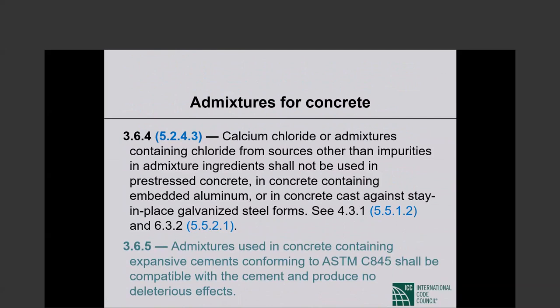Calcium chloride or admixtures containing chloride from sources other than impurities in admixture ingredients shall not be used in pre-stressed concrete, in concrete containing embedded aluminum, or in concrete cast against stay-in-place galvanized steel forms. This is extremely, extremely important. Wherever you have potential corrosion, any situation where you absolutely need to make sure that there will be no corrosion problem, you have to avoid calcium chloride in your admixtures. Okay, no calcium chloride in admixtures.